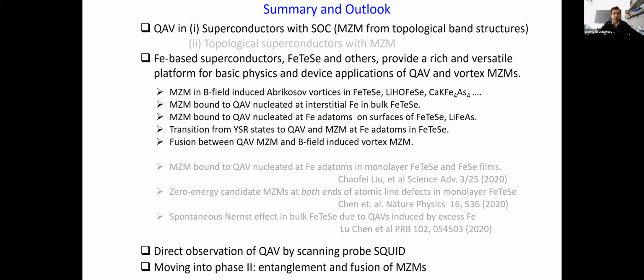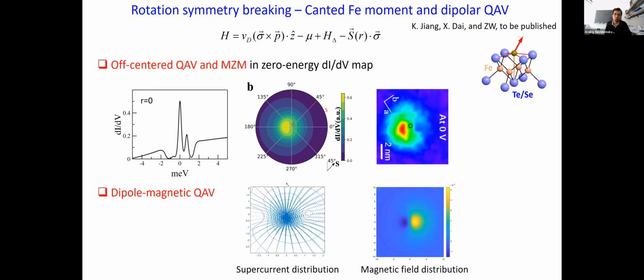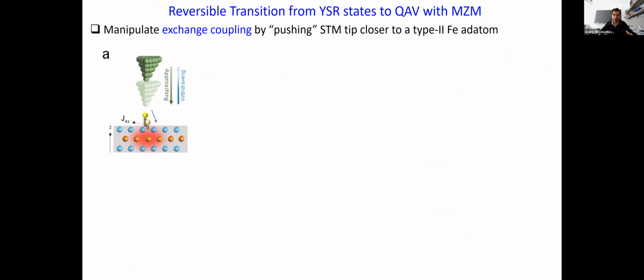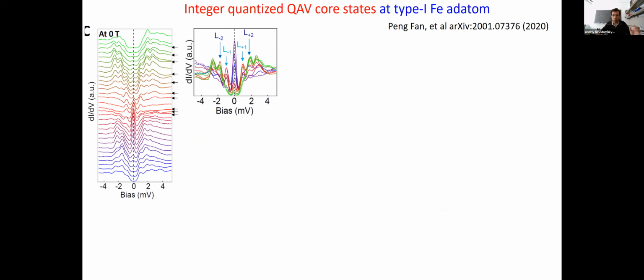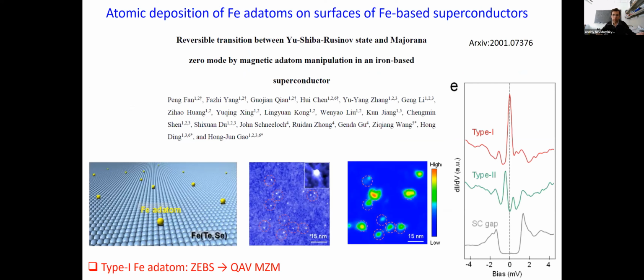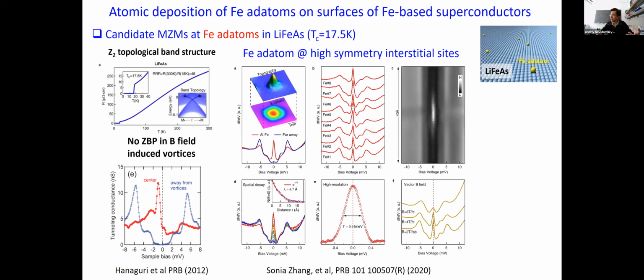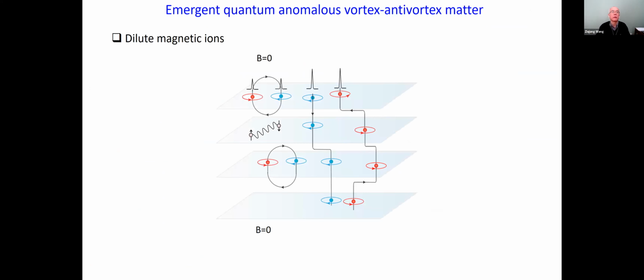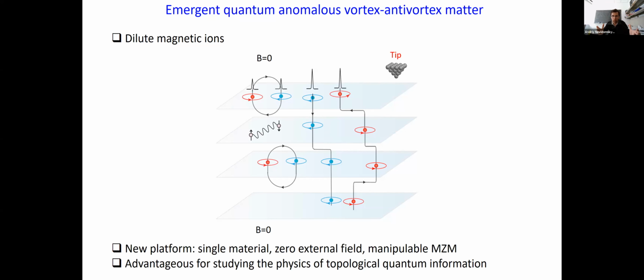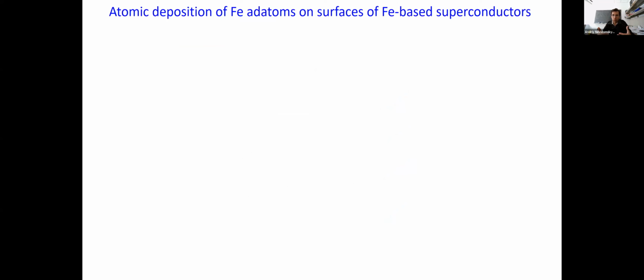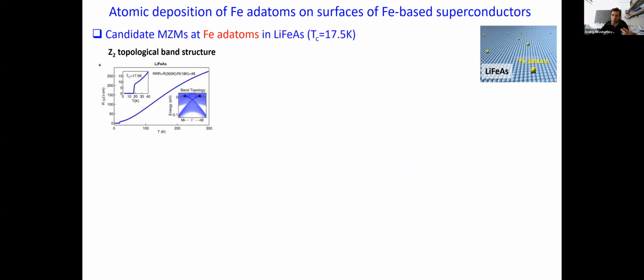Right. Zichang, I have a question about the energetics. So you've argued that fundamentally the reason why the quantum anomalous vortex would exist is because it preferentially would bind to a local adatom site, and the energy of nucleating that vortex exceeds the line tension, right? Yes. In 3D. Yes. Now, why would you have two kinds of adatoms? I mean, on the surface of it, the parameter that you care about is the ratio of something like EF squared over delta, right? Excellent. So, for a given material, the Fermi energy is fixed. So why, on the surface of, let's say, lithium iron arsenide, would you have two kinds of adatoms?